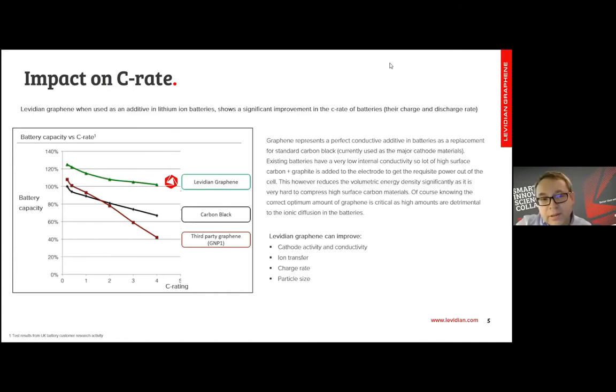I think the interesting advantage of the graphene which we are using from our process is that it has a fairly high surface area, and also a high amount of edges that comes with the graphene. The flake size is much smaller than what you normally see out on the market. That combination of active edges and the planar graphene structure gives you an interesting ability to stabilize the chemistry that takes place within the battery. That's precisely why we see an interesting stabilization effect, especially on the charging rate of this particular prototype unit that was made in the past.